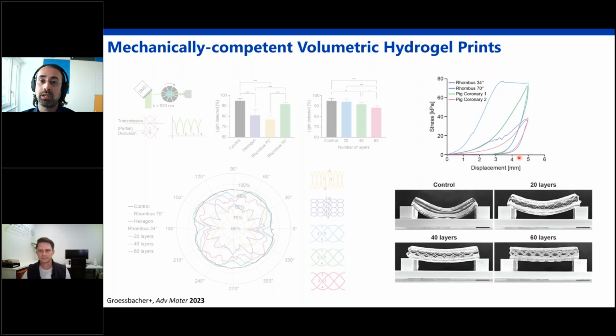In our experience, in our handling, the embedding is quite good. The adhesion of the gel to the PCL is quite good. It has been already investigated though in the context of non-cylindrical but more planar geometries with composites between hydrogels and meshes of fibers. Some ways are to improve hydrophilicity of the meshes, for example, by NaOH treatment or plasma treatment. Other ways are to use variations of PCL or other polymers that can form covalent bonds with the gel, and that improves adhesion already.